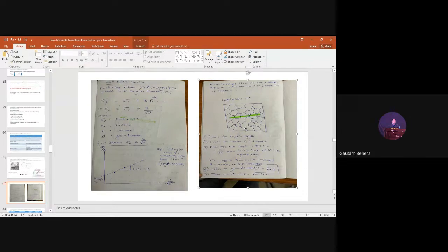Okay, fine. There is a technique to measure the grain size in a material that is called the linear intercept method. In this linear intercept method, we first take a microstructure with the help of a microscope, and we know the magnification. Suppose the magnification is M. We can see multiple grains here. So we have to draw a straight line, and we have to know the length of this line. Suppose the length of the line is L, capital L.